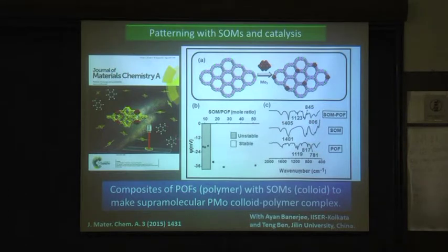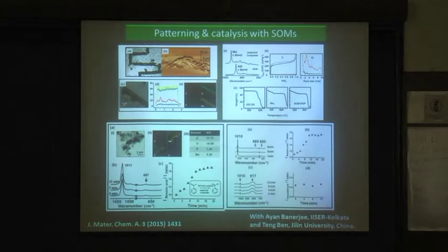and that is why we chose this, and we characterized this of course in the dispersion mode with attenuated total reflection, and we measured the zeta potential, and we see that we get an unstable regime, but we can move on to the stable regime which changes back into the unstable regime. So, we chose the stable regime, and then we decided, okay, fine, now can we make patterns out of it. So, we wrote the patterns, we scraped out from the pattern, and we saw indeed on the very nanoscopic scale we have a phosphomolybdate supramolecular composite. So, that means we can do catalysis with it,